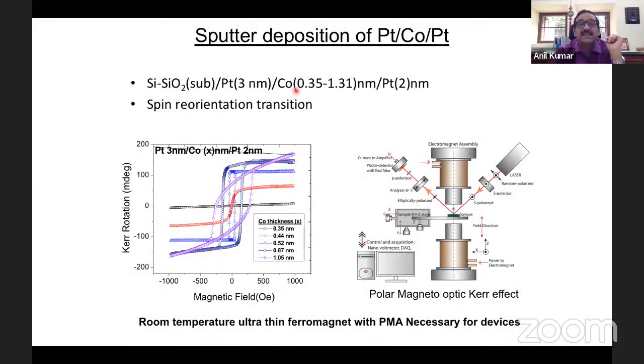Suppose I vary the cobalt layer thickness between the 2 platinum layers. You see that there is a critical thickness below which the cobalt is magnetized perpendicular. Above 0.8 nanometer, 0.9 nanometer, the magnetization goes in plane. So between a small window of 0.3, 0.4 nanometers to say 0.8 nanometer, the magnetization of this ferromagnet, the cobalt, is perpendicular to the plane.